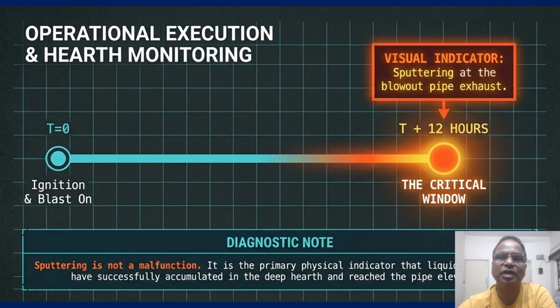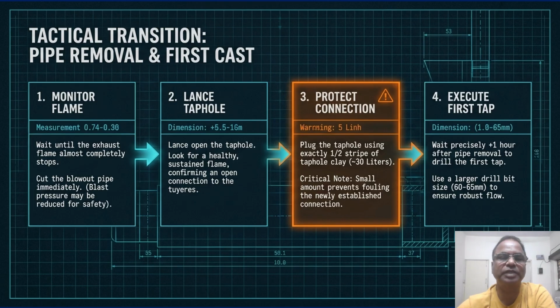So first cast: this four-step flowchart outlines the transition. Step 1, monitor the flame. Once it has almost stopped, you cut the pipe immediately. We often reduce the blast pressure here for safety. And step 2, as you can see, lancing the taphole until you see a healthy, sustained flame, confirming the connection of the two.